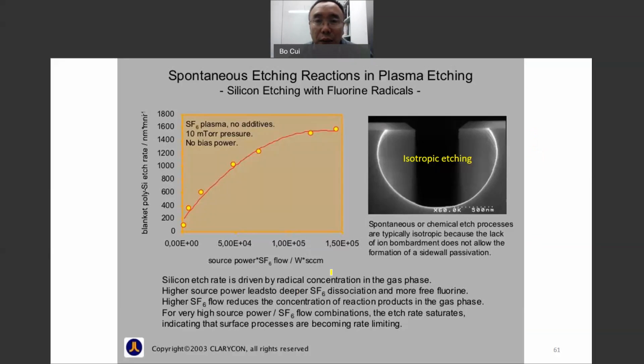So here is an example of the etching of silicon using SF6 plasma. As we said, the etching is isotropic. The higher the power and the more the flow, the higher the etching rate. In this example, it gave about a 1.6 micrometer etching rate, then got stabilized. For a modern etching machine, it can go really fast. For example, it can etch 50 micrometers per minute. It's very, very fast.